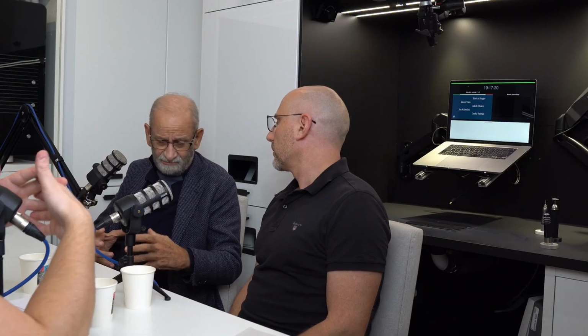Mine is about 12 hours. Yeah, this is very good. Twelve hours is very good. You go up slow and you go down slow. If it's a single unit, then you can go a little bit faster. But if you have very huge restorations, with a big volume and very heavy, you always have to do a slow treatment. I always do slow treatment. This is the best. Go slow.